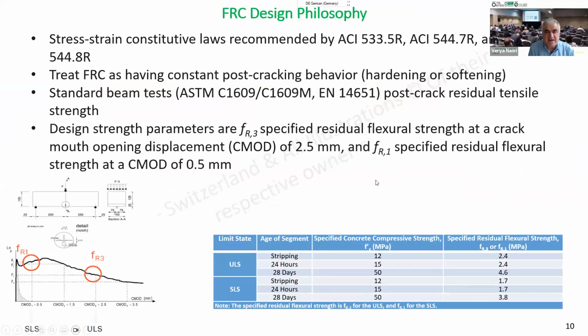Now we start the fiber concrete design philosophy. We have to use the stress-strain, basically a constitutive relationship, from these ACI documents. And we have to consider constant post-cracking behavior. We usually use a standard test like ASTM or EN to determine the post-crack residual tensile strength. You see these tests, for example the beam test, where we apply the load, measure the crack opening, and draw this curve. At FR1, when the crack is open 0.5 millimeter, we use that residual strength for SLS. And when the crack is open 2.5 millimeter, we use that parameter FR3 for ULS.